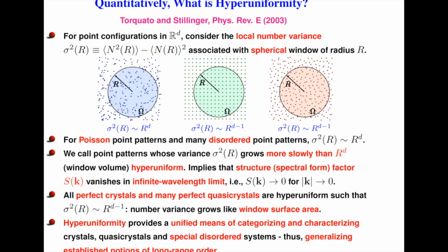And if you think about time, you might be taking snapshots later in time if the relaxation time is small. Usually, if you have a glass and you pass the glass transition, the relaxation time is very, very large, so you're not going to have to worry about any kind of dynamic changes. But the point is that what we're talking about here is taking snapshots of the system. And if you have a large enough snapshot, you can get the information about the density fluctuations by probing that, or large enough windows, say, for a range of window sizes. Does that answer your question? Yeah, thank you.